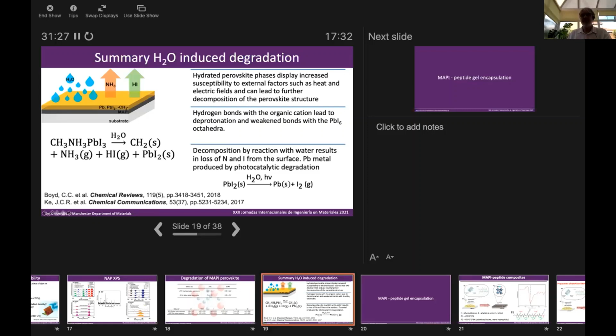The problem with this is that the hydrated perovskite phases also increase the susceptibility to things like heat and electric fields. Electric fields can cause iodine migration in these materials because the anions are quite mobile. As you probably know, perovskite oxides are chosen for things like oxygen permeation membranes and fuel cells because the oxygen mobility, the anion mobility, in perovskites is quite high, and that's the same here. When you apply an electric field, the iodine ions will tend to drift towards the positive electrode. So these are some of the work: the first one is the one that talks about the hydrated perovskite phases. The second one is our NAP-XPS study that I've just talked about.